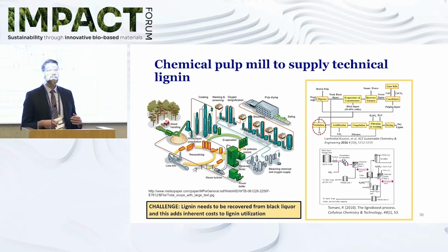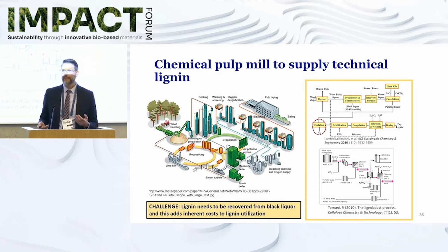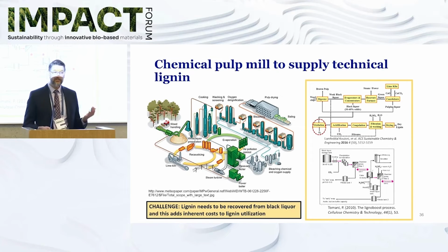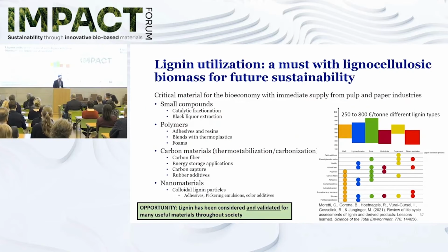The one issue though, when we talk about lignin, usually people talk about how cheap lignin is, and so it is cheap if you compare it to the heat equivalent value of the lignin, and so that's used to make a significant amount of energy at the mill. But when you begin to do this process of lignin recovery, you need chemicals, you need the actual infrastructure, you need the labor to do that, and so that actually drives the price of lignin up, and so you have to have applications where you can recover that price of lignin recovery.